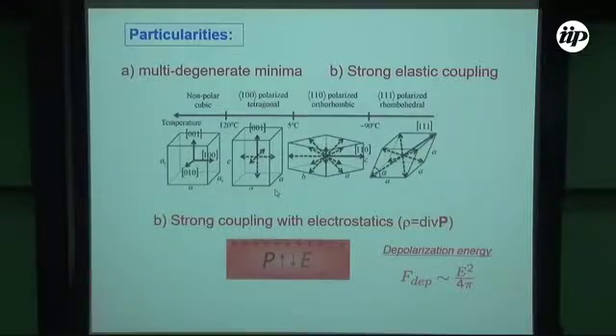The second aspect that is very important is that the displacement of the center of the polar atoms is strongly coupled with elasticity, and the deformations are quite large, something like 0.3%, which is a huge value. So elasticity strongly participates in the phenomena in the crystal, and because of this, the inverse side is that we can really play with it and tune the phenomena by some kind of stress, strain, and so on. And the last one, it's B, so it should be C, which for me is possibly most interesting, is the enormous coupling also with electricity.